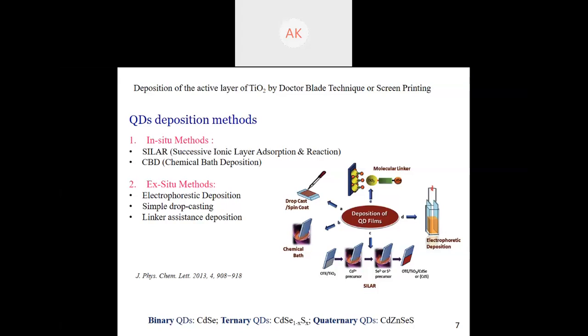So it is easier. Ma'am, how are you controlling its size? Because quantum dots are very sensitive to size. Yes. Now, as I said, in the in situ method you sometimes lose out on the size control. So what we do is we monitor the dip time, the concentration of the solution, how long we are dipping it, and how fast we are withdrawing it from the solution. These things control the size. There is something called the withdrawal time, that is how fast you withdraw the film from the solution and how long you keep it immersed. So these things affect the size.